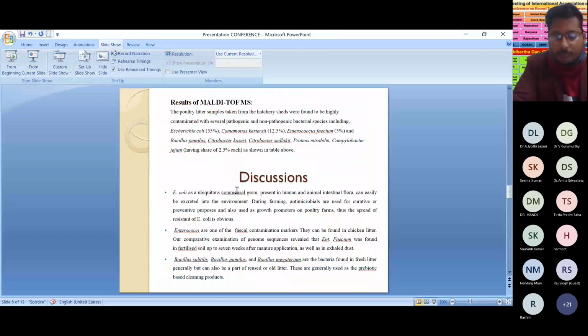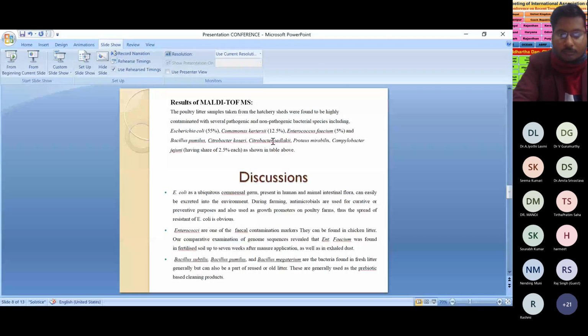The poultry litter samples taken from the hatchery sheds were found to be highly contaminated with several pathogenic and non-pathogenic bacterial species, including E. coli to be the maximum, that is 55%, Comamonas species 12.5%, and Enterococcus faecium 5%. There were also some other bacterial species, for example, Bacillus pumilus, Citrobacter koseri, Citrobacter sedlakii, Proteus mirabilis, and Campylobacter jejuni, having a 2.5% share. Now the discussion.